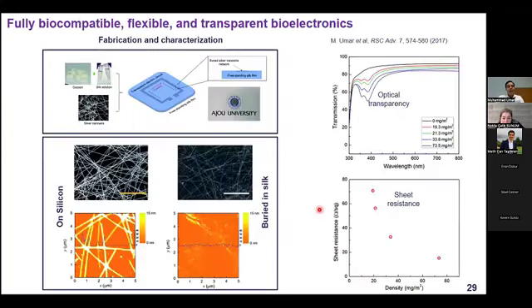So therefore, we utilize silk to make our device biocompatible and also transparent. Silk is transparent; its optical transparency is nearly equal to the optical transparency of glass. So in this case, we make some electrodes in the form of resistor and antennas, and we put silk onto that. These electrodes are made from silver nanowires. When we put the silk, these silver nanowires are fully buried inside the silk. And here you can see the pattern. So silk is transparent, and also the silver nanowire part is transparent.